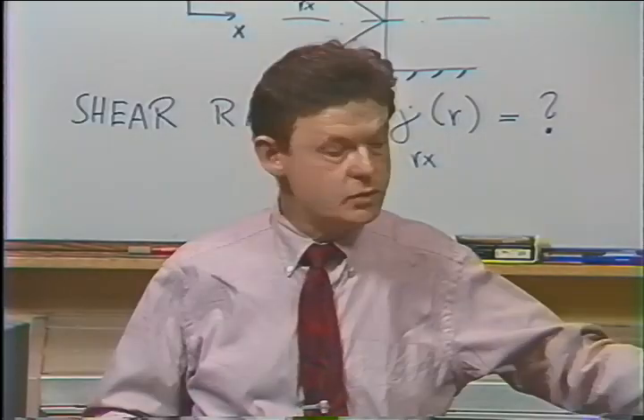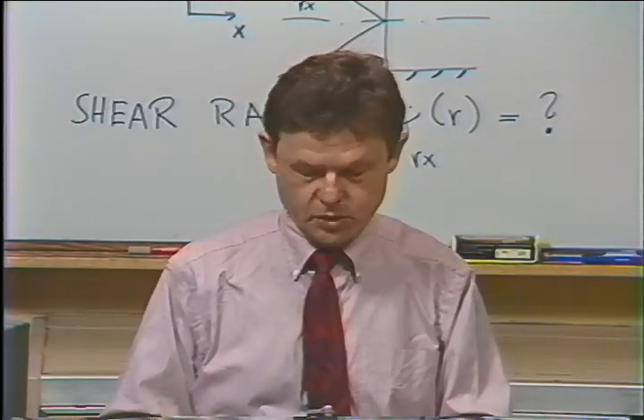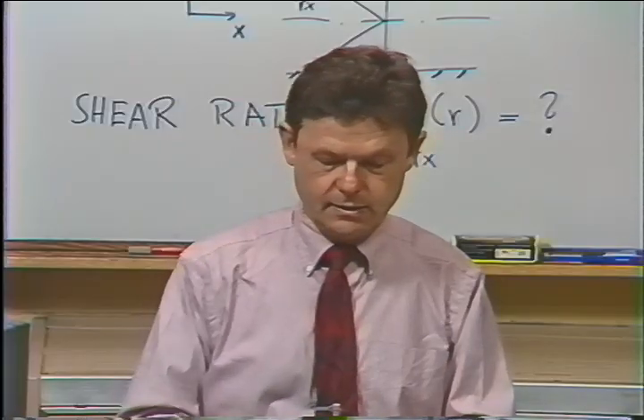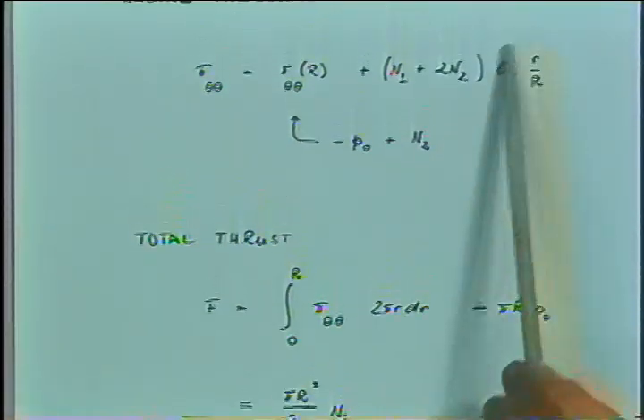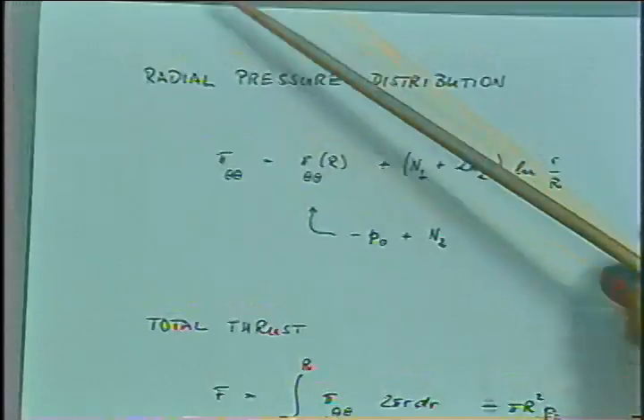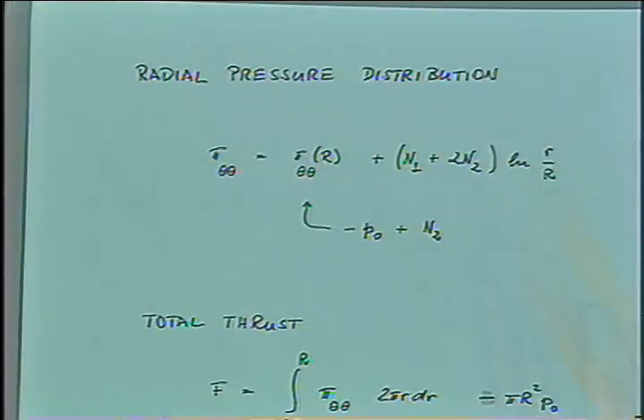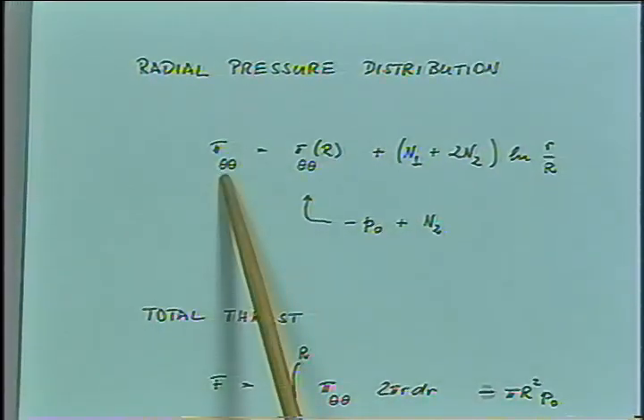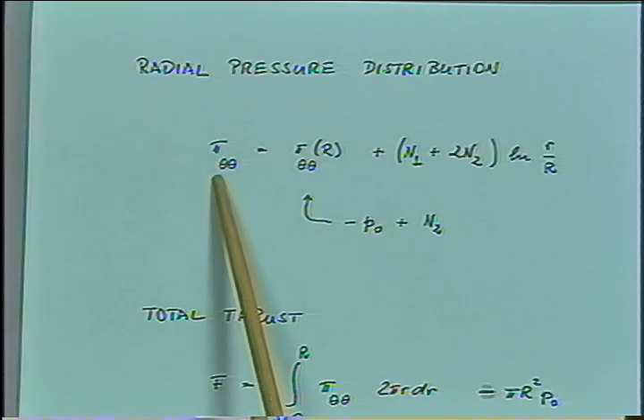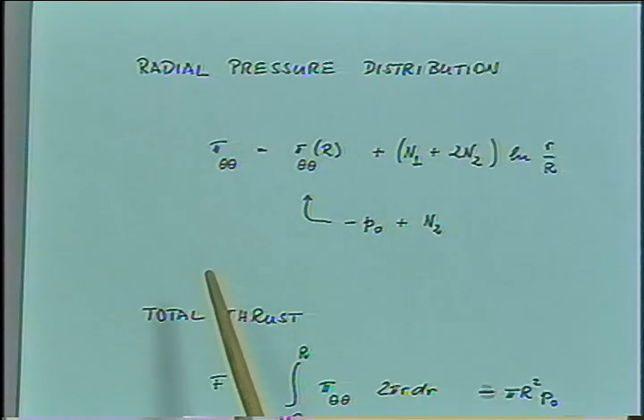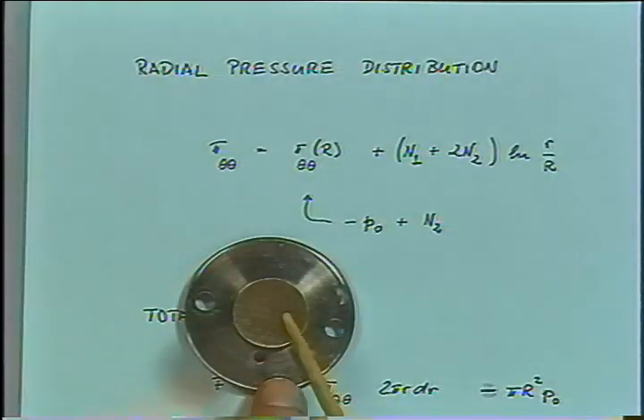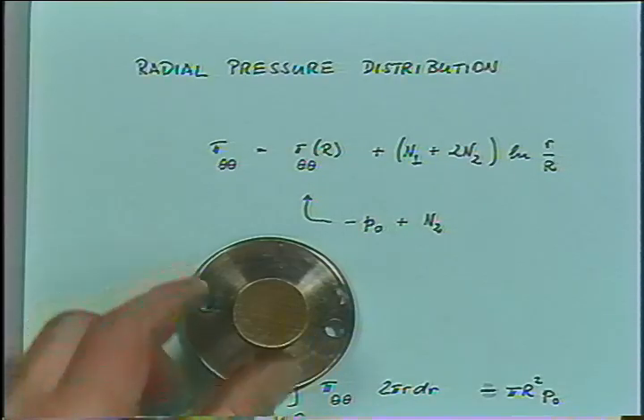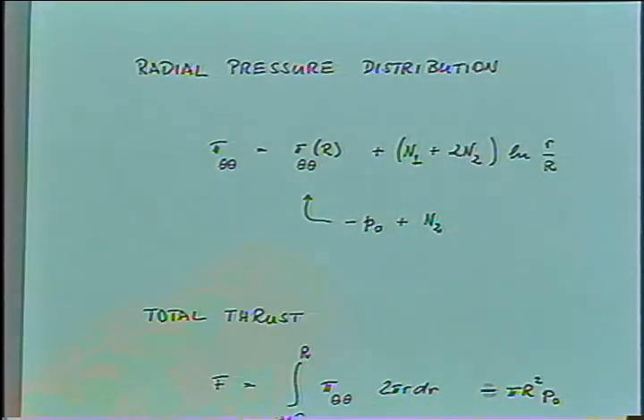We can integrate this now to obtain the distribution of the normal stress. It's actually linear in log R, so it's a linear stress distribution in this case. And note the normal stress distribution: the normal stress which a pressure transducer on the plate would measure, if we have a transducer here, that's if we would say have holes here and measure the stress normal to that system.